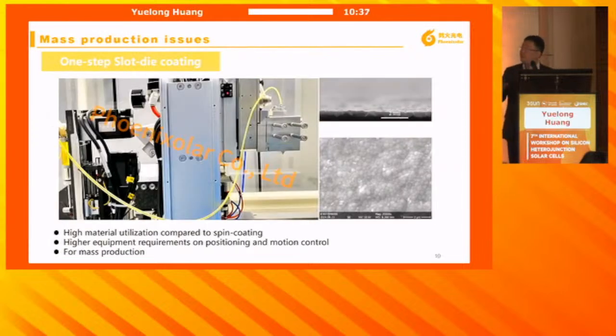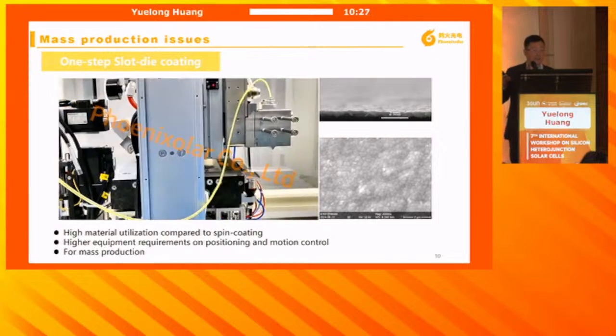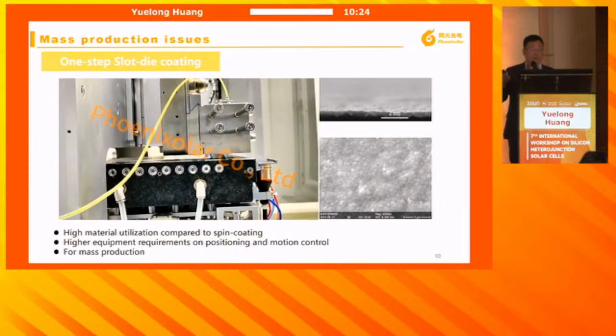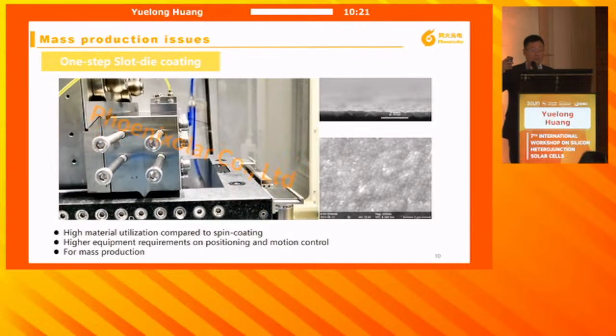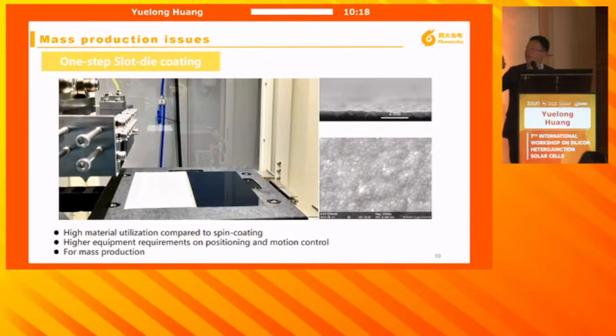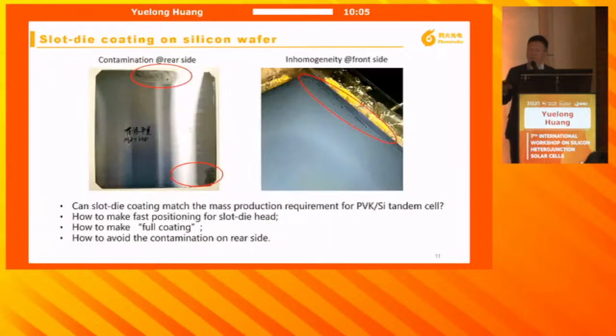Here I just show something about the slot die. The photo was taken by hand with a cell phone. Therefore, you see a lot of shaking, but in fact, the machine itself is stable. This is a slot die made by us. So when you are making the 4-inch slot die film, if you look at the SEM and XRD, you can make a good film. But the problem is that you cannot make a very good film for the 4-inch wafer. It's always difficult to avoid contamination from the rear side, or to make a full coating, especially at the edge.